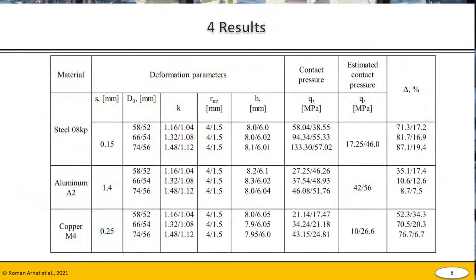number 8. In the table, the numerator gives the values of the diameter, the draw ratio, the stroke of the punch, and the value of the contact pressure related to the drawing option with the rounding radius of the die body RM 4 millimeter. In the denominator, it's the same for RM 1.5 millimeter. Delta in percent is the deviation of the experimental data from the theoretical ones. Next slide.